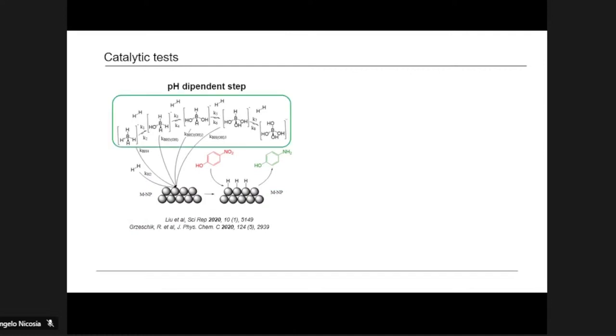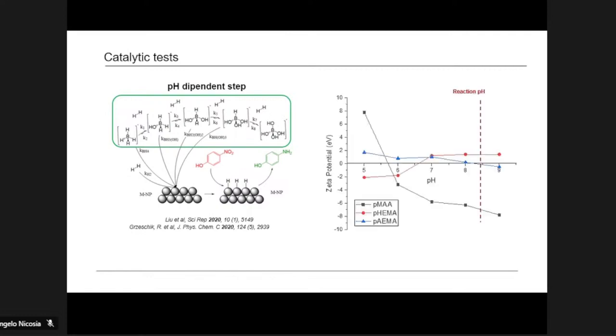Analyzing the mechanism, we observed that the acidity of the system can influence the hydrolysis of the sodium borohydride inside the catalytic mechanism, so each step is pH dependent. To confirm the effect of the functional group, we analyzed by a titration as a function of the zeta potential to observe the real surface charge at the pH of the reaction, and the only sample that exhibits a negative charge is the system with acrylic acid monomers.